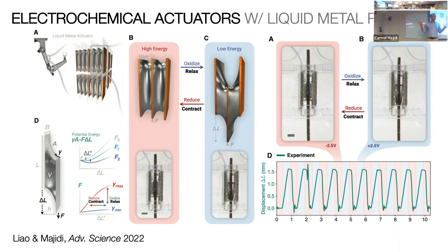It's about 10 times higher surface tension than water, right? So close to a joule per meter squared, which is pretty extraordinary. And then by applying a little bit of voltage, we grow an oxide skin, just a few nanometers, right? What that does is basically kill the surface tension. It goes from like 0.7 joules per meter squared down to virtually zero.